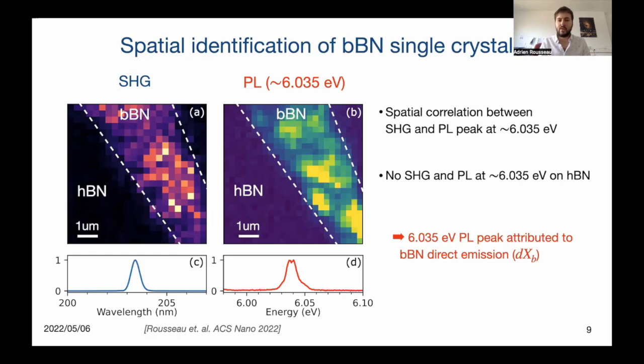By performing now the photoluminescence intensity map at the energy of 6.035 electron volt on the same area, we observe that the photoluminescence intensity peak is strong only in the Bernal boron nitride region and vanishes in the hexagonal boron nitride region again, as you can see on the second picture.